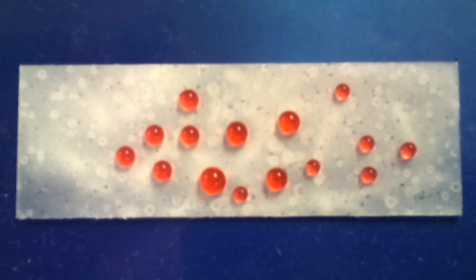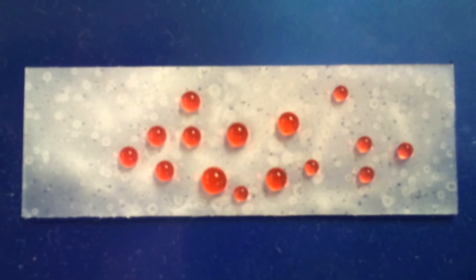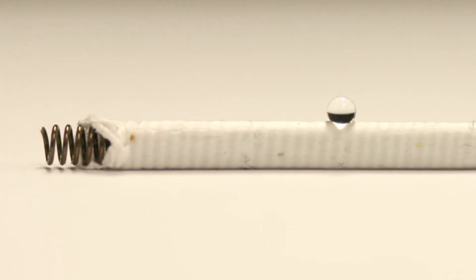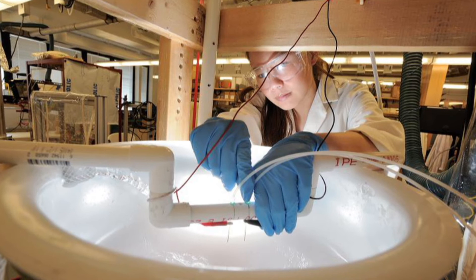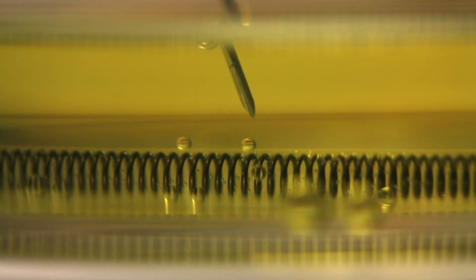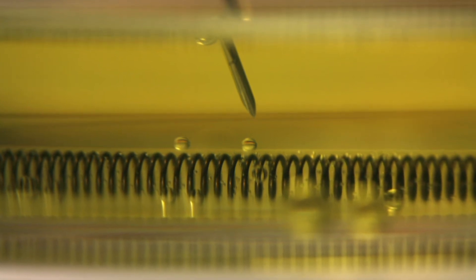Some of the other applications involve looking at the structural properties of the mat. Those mat structures have a much higher contact angle with liquid drops, and when the contact angle is greater than 150 degrees, it's referred to as super hydrophobic. We have studied the super hydrophobic mats as flat sheets, where diesel fuel would flow through the flat sheet as a normal filter media and water droplets would collect on the outside of the sheet.